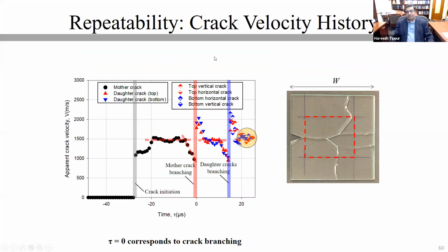We have done this experiment several times, and I want to show you one where things were not very symmetric, and see if the same idea holds good or not. So this was a repeatability experiment where we had, you can look at the right-hand side here, the crack has propagated, but the very initiation ended up being a mixed mode crack instead of being a mode 1 crack. These are the difficulties of an experimentalist. And we produced a mixed mode crack, which eventually became a mode 1 crack, and then 2 daughter cracks and 4 granddaughter cracks.